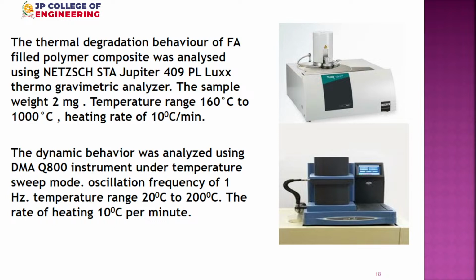This is to check thermal degradation. The top picture shows the thermogravimetry analyzer. Gravimetry means weight: as you increase the temperature, how the mass deteriorates. It starts to undergo degradation, meaning burning, so it undergoes a loss in weight. This is normally done to analyze how the material loses its weight over a temperature range, at a selective heating rate of 10 degrees per minute. We went from 160 to 1000 degrees, which is the critical range when it started degrading, where we carefully observed how it behaves.